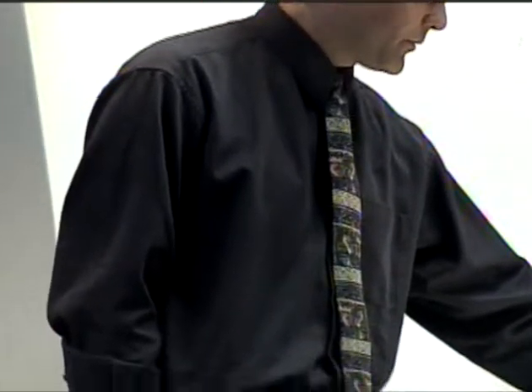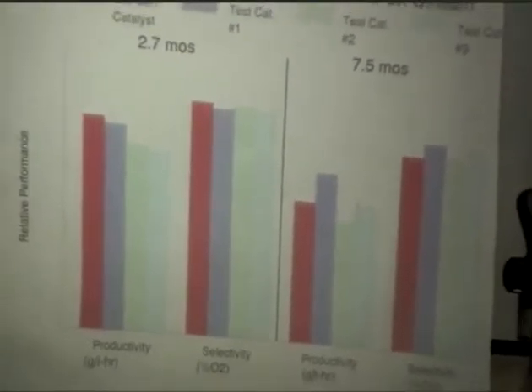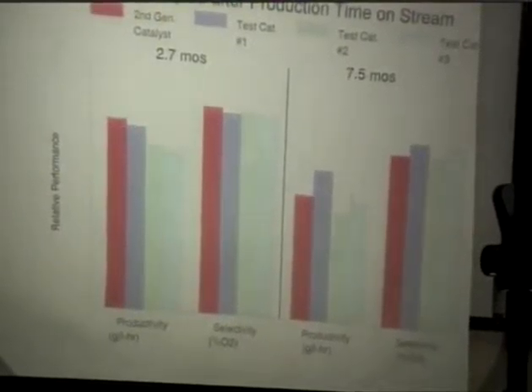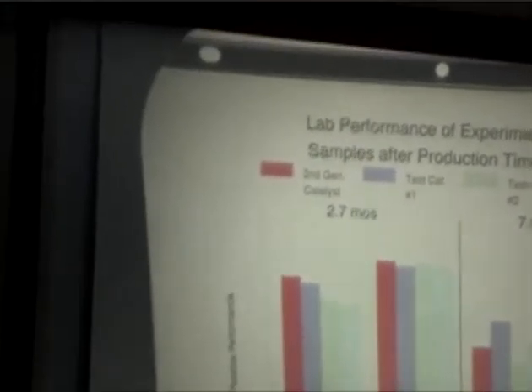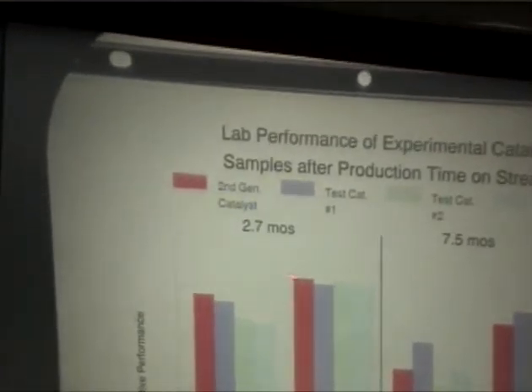As I said, we removed samples from the reactor at 2.7 months and 7.5 months. And what we found is that as we tested those in the lab, at 2.7 months, the productivity of our second generation catalyst, and in this case, what we're focusing on is our #1 test catalyst, were comparable. Maybe a little bit better activity out of the second generation catalyst. And then the selectivities are all comparable.